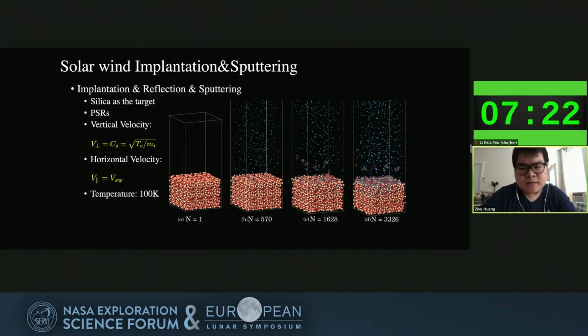And after each implantation, we relax the surface to the original temperature, which is about 100 Kelvin, making sure there's no energy residue before the next implantation cycle. The blue particles are hydrogen, and we continue to implant more hydrogen atoms. As the number grows, we can see more and more particles are reflected. This reflection of solar wind is consistent with observation by Kaguya and also Chandrayaan-1, but it's not a focus today. And after we implanted about 3,000 hydrogen atoms, we can see the surface is almost covered by hydrogen atoms.